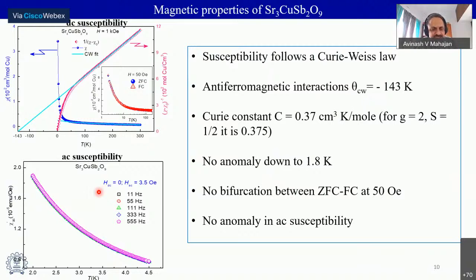If one looks at the AC susceptibility, essentially in low field, so small amplitude of the AC field, there's really no telltale feature as a function of frequency or as a function of temperature. There's nothing happening. One just sees a Curie kind of behavior. So there is clearly no evidence of any freezing or any kind of ordering. Okay, so the first criterion is met in the bulk probe. You have a strong antiferromagnetic interaction, but no evidence of long range order or even any kind of spin glass order.